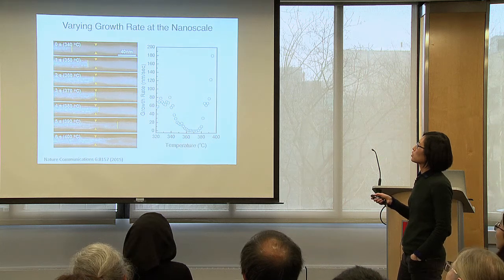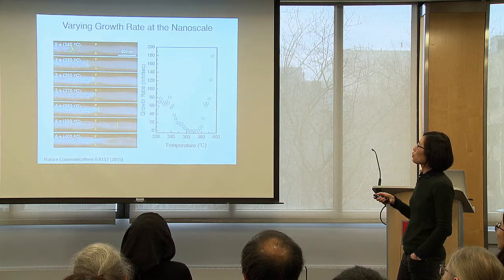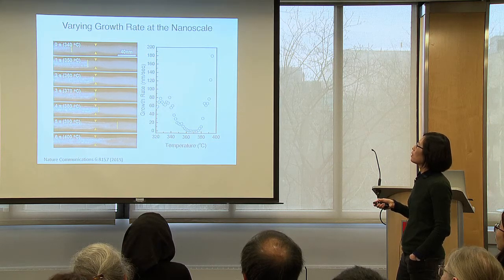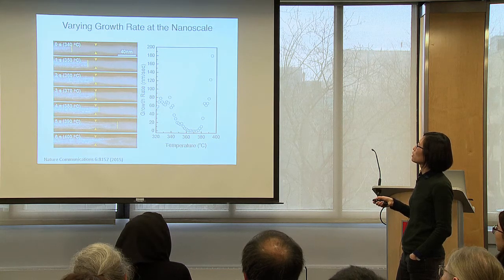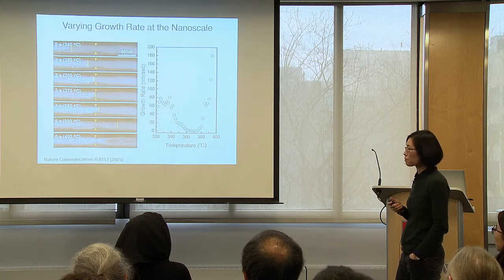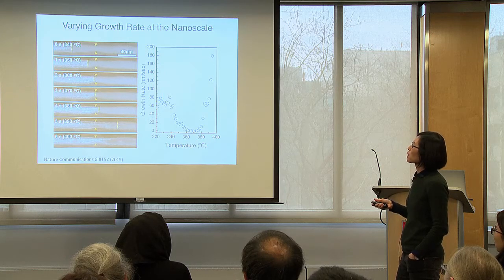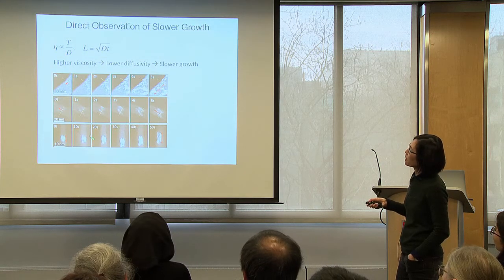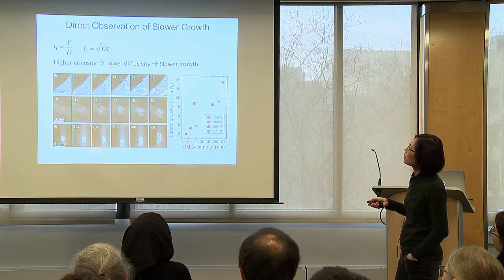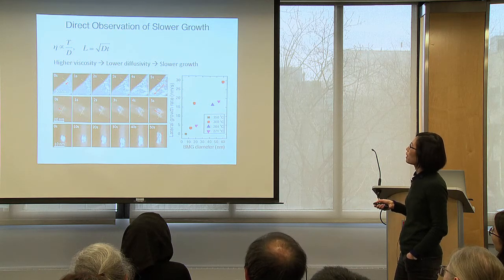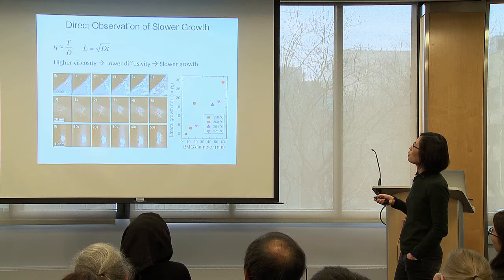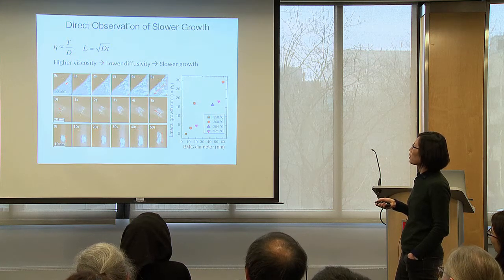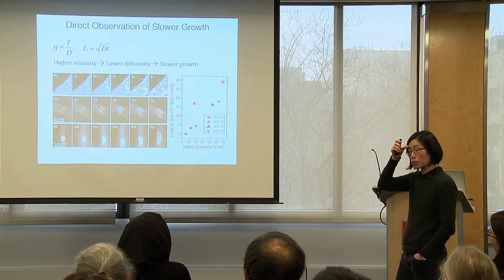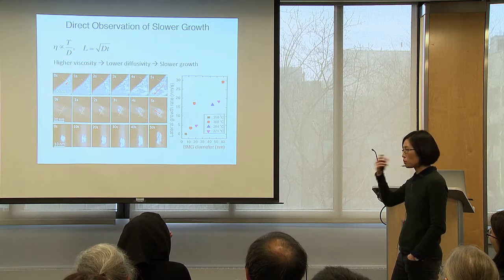So here are just snapshots showing the growth front. And so we were ramping here. The temperature here is somewhat of a time series. And then you can see that right at the necking region, the growth rate is greatly suppressed. This is not just because of the necking. So here, these are all various diameter nanorods. And what we're saying here is that when we look at the growth rate as a function of diameter, the growth rate is also small for smaller rods. Okay? So this is pure observation.